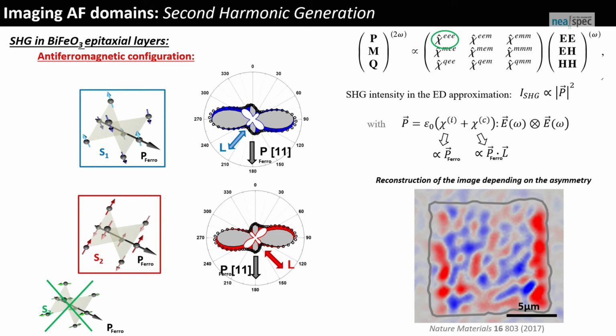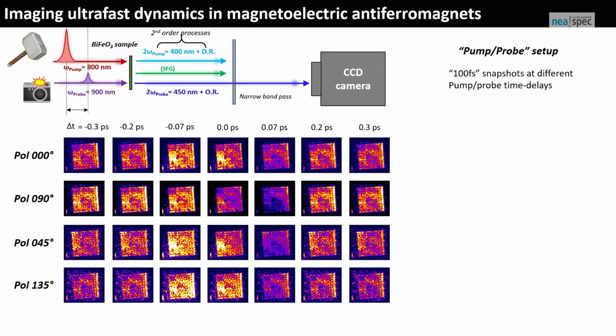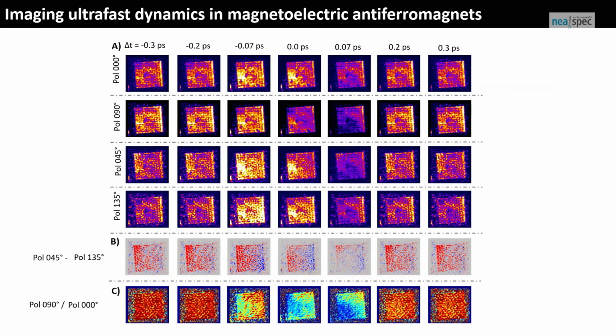But then, as I said, we're also interested in the dynamics, so we can move to, let's say, a pump-probe time-resolved experiment. Now we still have a probe which is second harmonic generation, and we pump with a large, intense femtosecond pulse. Then we can take snapshots of our structures at different delay times, and do a bit more analysis than just looking at the asymmetry, but okay, I will skip this. But the asymmetry gives us the red and blue domains, especially well before T0.